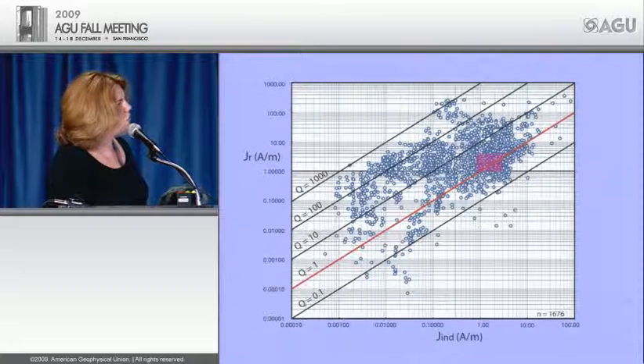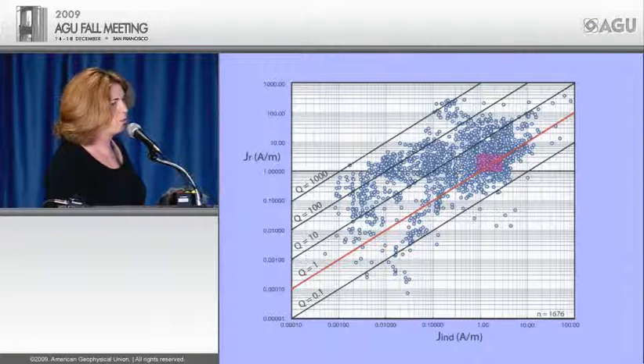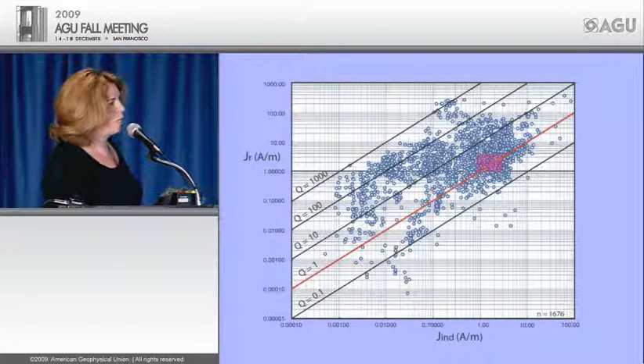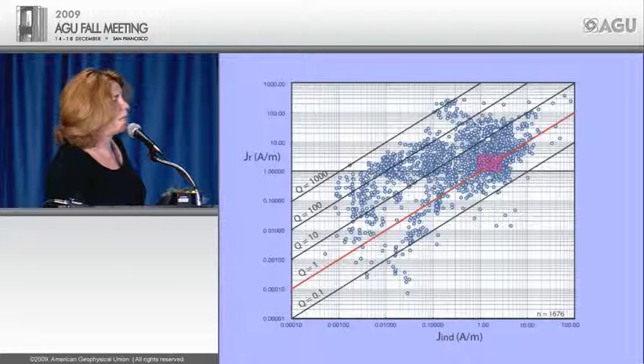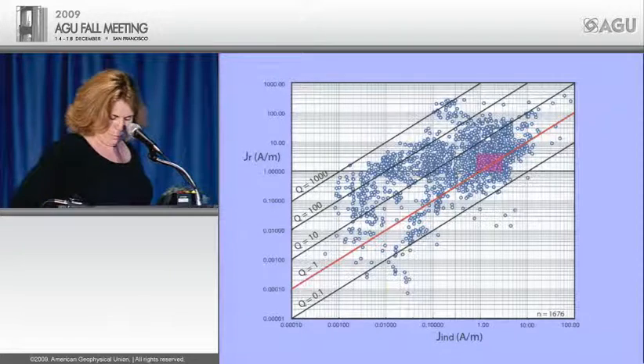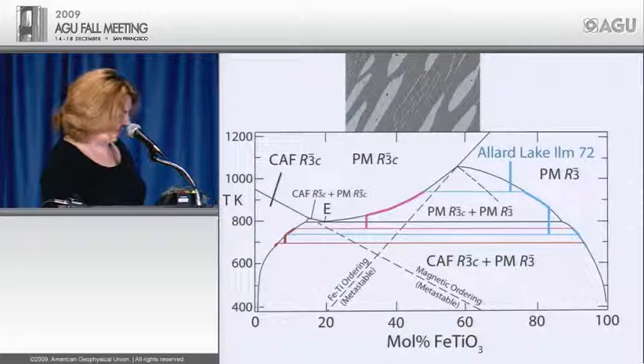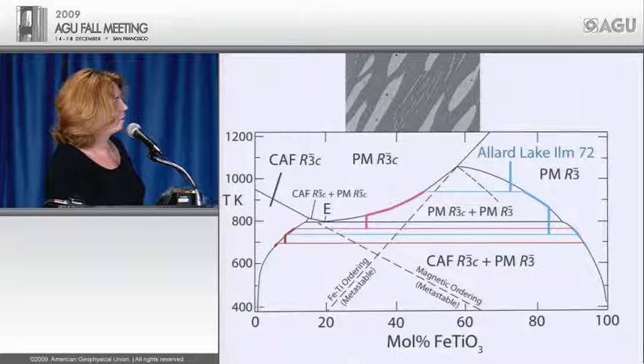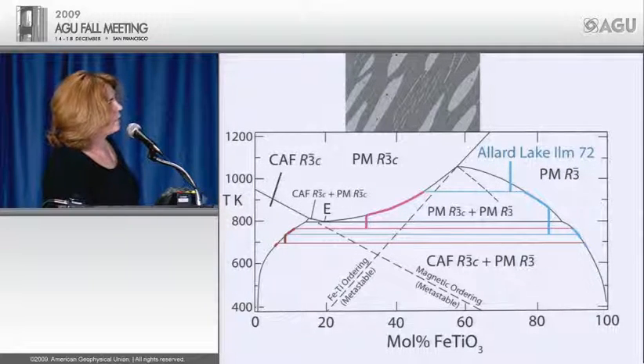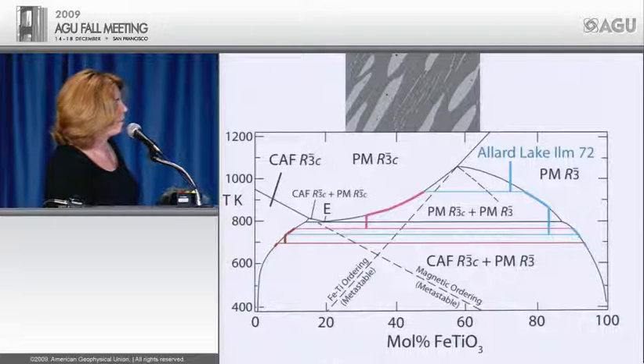The Q values are very high, and of course we're working with a lot of material here. The ores are, you know, nearly 90% of a lot of the samples, so you'd get very high remanences. The susceptibilities vary. Some samples have multi-domain magnetite, most of them don't, but we do see that. So here's the path of crystallization that we would have taken with Allard Lake. It had an approximate original bulk composition of around 72.